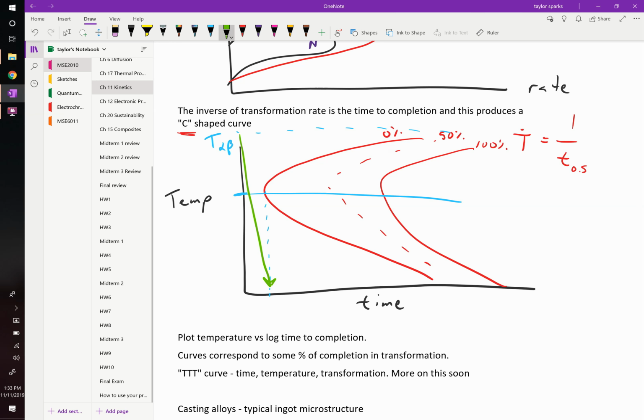So as you cool it down at different rates, you're going to get different phases forming. If you quench it in water, which is a really aggressive quenching medium, then you might get a metastable phase. Whereas if you cool it in oil, then it might go through the middle of that TTT diagram. So what happens? Let's say you take it out of the furnace and you immediately put it in a separate furnace. If you quench it down to here and then you put it in a furnace out to here, you still get 100% transformation. It's no different than if you took it here and quenched it across that line. In either case, it's going to start to transform the second it touches that line. It's going to continue transforming all the way until it's 100% transformed.